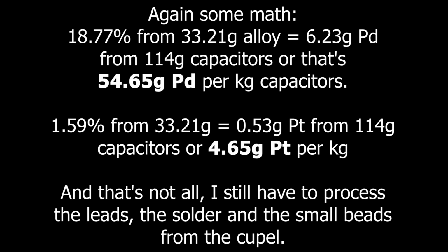Again some maths, 18.77% from 33.21 grams alloy equals 6.23 grams palladium from 114 grams capacitors, or that's 54.65 grams palladium per kilogram capacitors. 1.59% from 33.21 grams equals 0.53 grams platinum from 114 grams capacitors, or 4.65 grams platinum per kilogram capacitors.